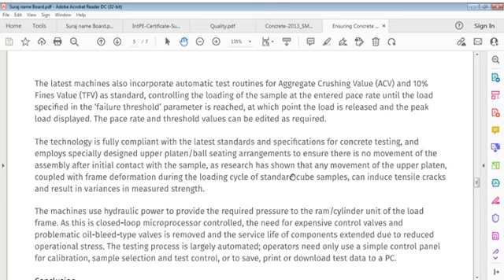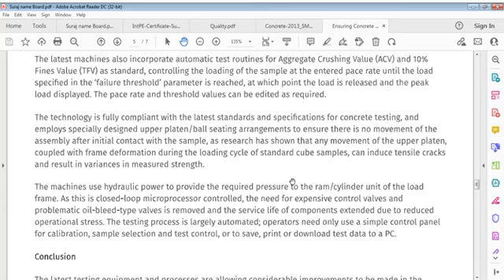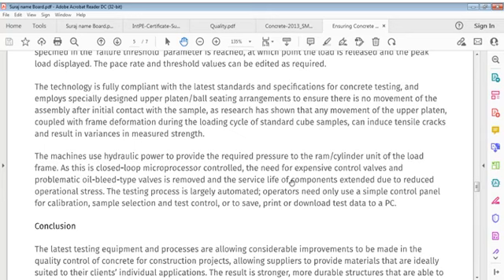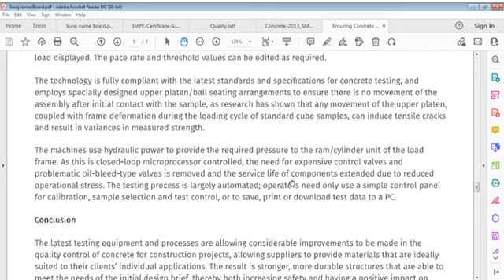The technology is fully compliant with the latest standards and specifications for concrete testing and employs specially designed upper platen ball seating arrangements to ensure there is no movement of the assembly after initial contact with the sample. Research has shown that any movement of the upper platen, coupled with frame deformations during the load cycle of standard cube samples, can induce tensile cracks.